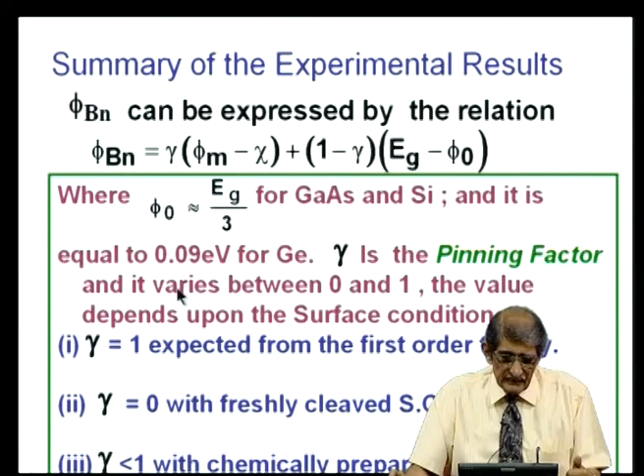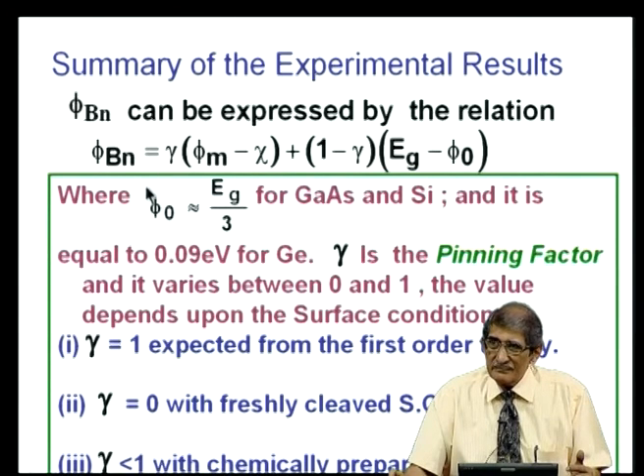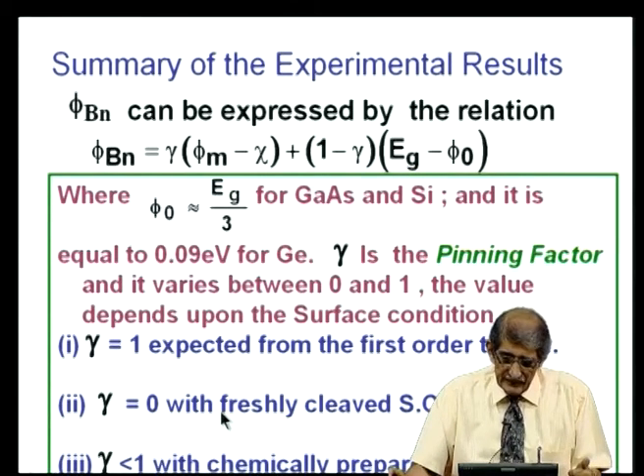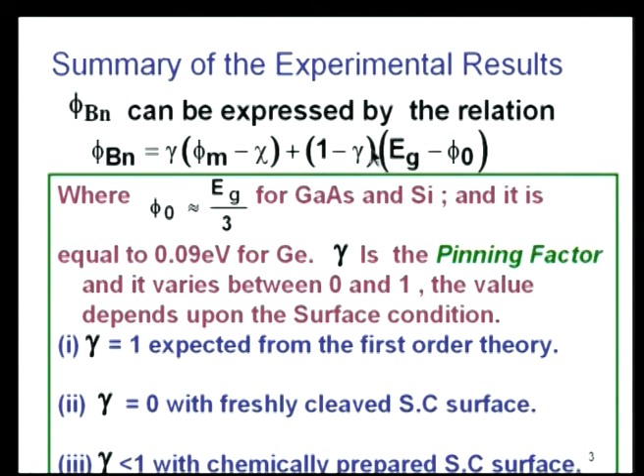So, gamma is called the pinning factor and it varies between 0 and 1. The value depends upon the surface condition. Gamma equal to 1 is expected from first order theory, phi b n is phi m minus chi. We saw that if gamma equals 1, that is ideal. Gamma equal to 0 is for freshly cleaved surfaces, and means phi b n will be independent of phi m. For freshly cleaved surfaces, we saw that phi b n is constant, independent of work function. You can immediately correlate that in a freshly cleaved surface, the surface state density or interface state density is very high. So, you could guess that the entire deviation from ideality is due to the presence of surface states, which we did not take into account in the ideal theory.